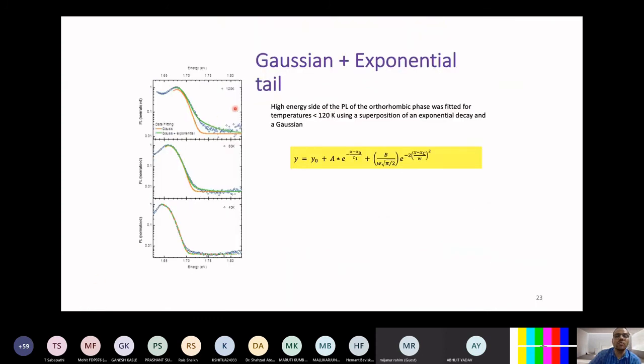Further, we could explain this by fitting our photoluminescence data. If you do a PL experiment and fit your data at 100 Kelvin using a Gaussian distribution, it doesn't fit very well. But if you fit with a Gaussian plus exponential decay, then it fits well. Why do I need the exponential decay? I know exponential decays are used in lots of tail states fitting. So is that something to do with that? We checked again by reducing the temperature from 120 to 80 to 40 Kelvin. The moment we go to the 40 Kelvin data, we find that if we don't use the exponential term, we can fit the data okay.